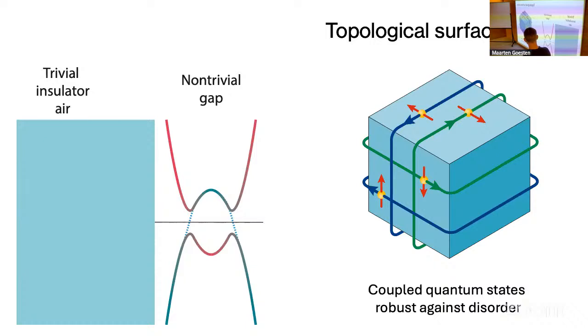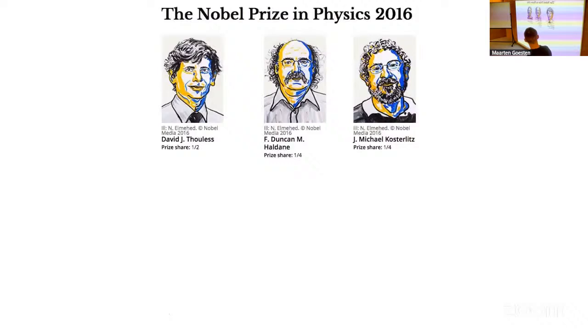Because your electronic states cannot go smoothly from here into here. They go through a transition, a gapless region, and actually what you get is topological surface states. Those are metallic gapless states that then emerge on the surface of those single crystals. And that is fully controlled by the energy ordering and the irreducible representations of the wave functions in the band structure. Now, this is what gave rise to the Nobel Prize in physics in 2016.